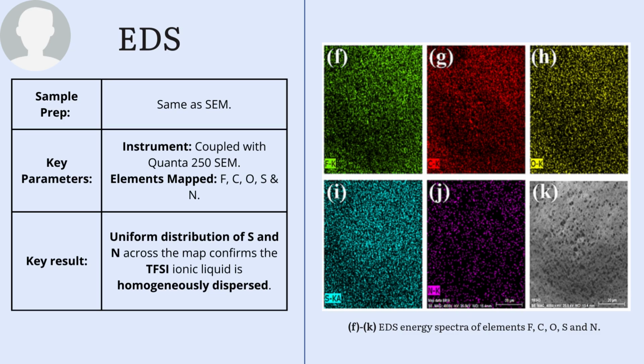Next one, a porous structure is only effective if the conductive elements are correctly positioned. Therefore, the SEM was coupled with the EDS to map the elemental distribution. The analysis specifically tracked sulfur and nitrogen, which serve as the unique markers for the TFSI ionic liquid.